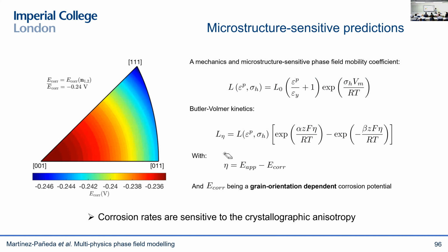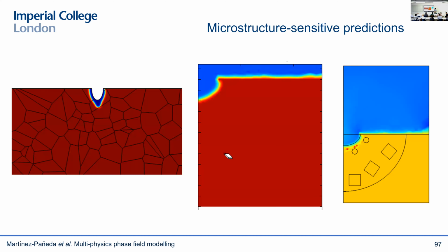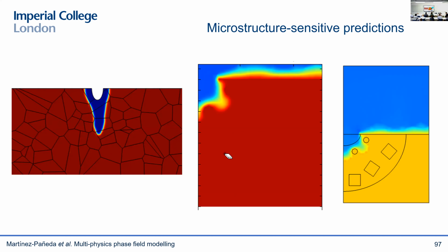We can also capture the effect of the microstructure. So we know from experiments that corrosion rates are sensitive to the crystallographic anisotropy. So we can define a grain orientation dependent corrosion potential, and therefore we're able to capture this different crystallographic anisotropy. And you can see here that this deviates from the kind of, I would say, mode 1 corrosion that you expect in an isotropic material. And again, you can also capture more complicated things like secondary phases and so on.